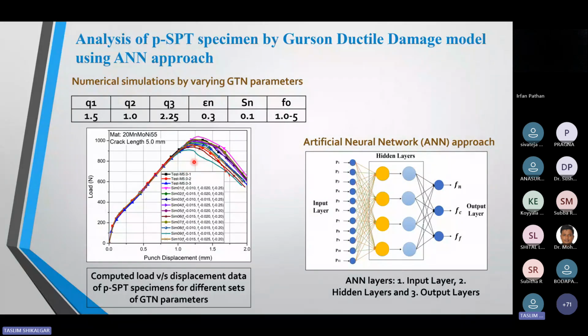So how to generate this database to train the artificial neural networks? I decided on the punch displacement. I finalized 15 punch displacement values like this, from this place, this place, this place. Once you finalize the punch displacement values, you cannot change them. If you change these punch displacement values for the experimental data, then again you get wrong predictions.